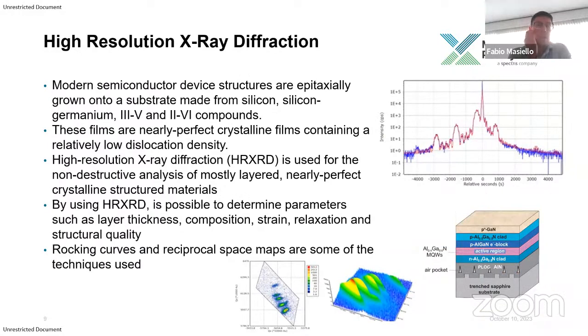Now, moving again into the realm of more single crystal, there is a whole bunch of techniques which make use of what's called high resolution X-ray diffraction. Here, high resolution means that the beam is highly monochromatized. While in powder diffraction you typically use a beam that has several wavelengths, for example K alpha 1, K alpha 2, and a bit of Bremsstrahlung, in this case you really want to have it as monochromatic as possible because you're looking at typically single crystal, and you're looking at